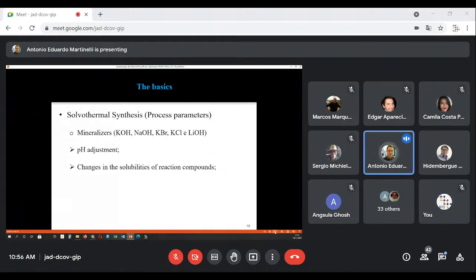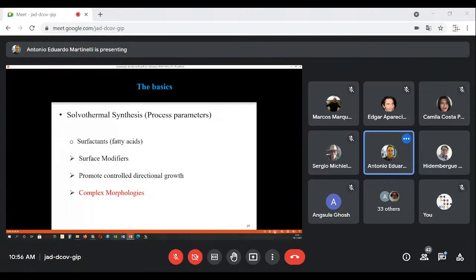In this case, mineralizers are substances capable of providing solubilization. Also, they are used to adjust the pH of the solution. These are the main mineralizers used in solvothermal synthesis. And we also make use of surfactants. They help control nucleation, phase homogeneity, size, morphology, and dispersion during crystal formation. They are usually amphiphilic fatty acids. That is, they have hydrophilic and hydrophobic constituents. Examples are sulfated esters or sulfates of fatty acids, anionics, and quaternary ammonium salts. So they also help when complex morphologies are needed to be achieved.